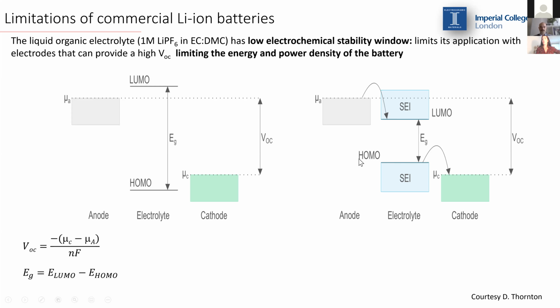If the HOMO of the electrolyte is above the electrochemical potential of the cathode, the electrolyte can be easily oxidized by it, and it will have a similar effect as before. And therefore, the open circuit voltage that we can have in our battery is going to be limited by the length of the energy bandgap between the HOMO and the LUMO of the electrolyte.